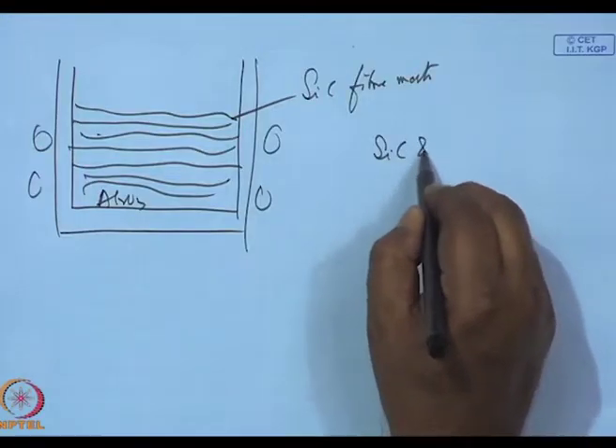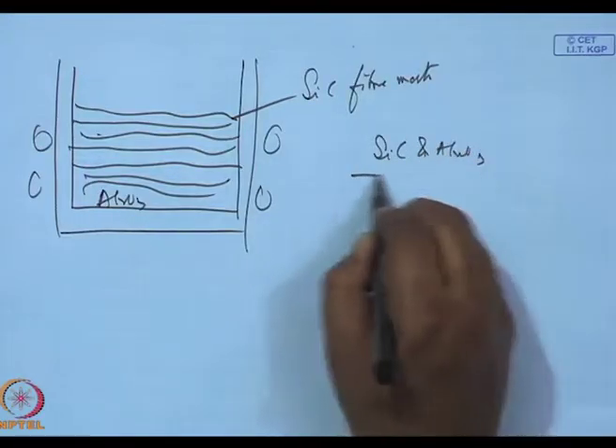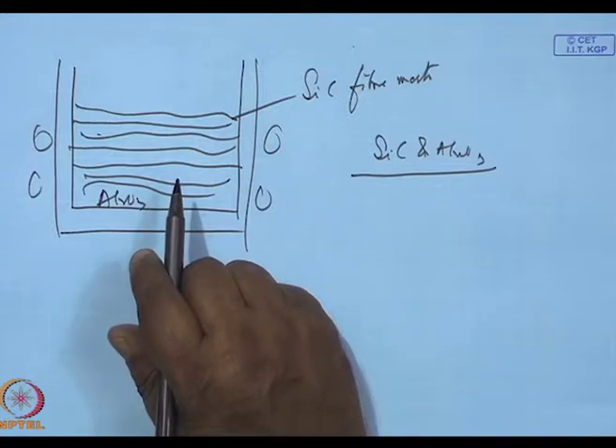At those temperatures, alumina will melt at 2075 degrees centigrade. There will be an interreaction between the silicon carbide and alumina, which would be disastrous. Why? Because if this is a silicon carbide fiber and the matrix is chemically bonded, it would not be acting as a composite. The alumina matrix would break and the silicon carbide fiber would break.